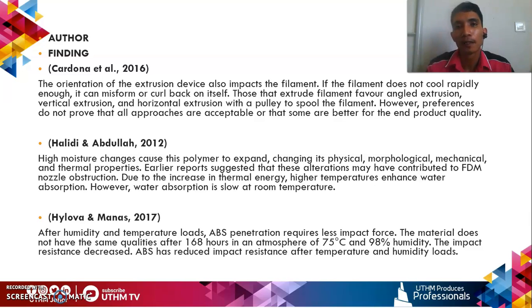For number 3, Hylova and Manas in year 2017. After humidity and temperature loads, ABS penetration requires less impact force. The material does not have the same qualities after 168 hours in an atmosphere of 75 Celsius and 98% humidity. The impact resistance decreased. ABS has reduced impact resistance after temperature and humidity loads.